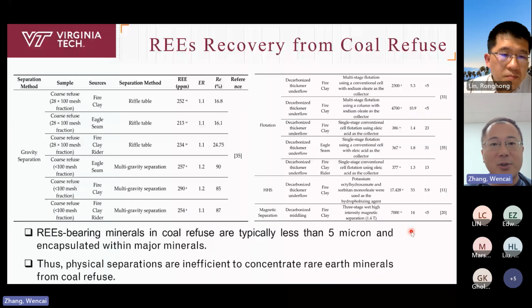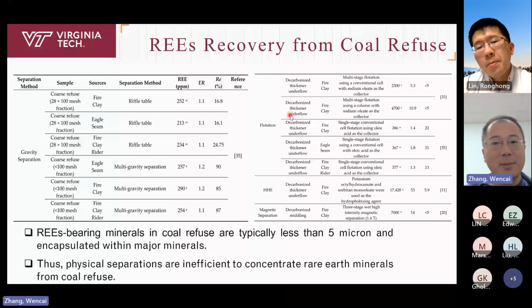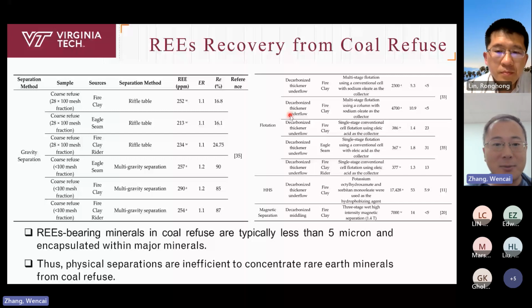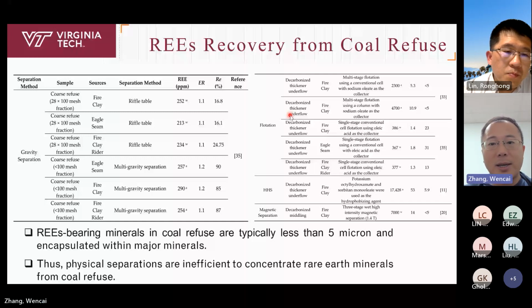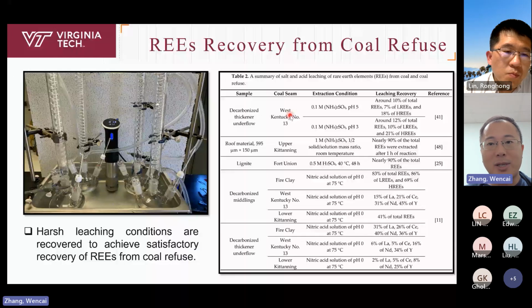So we did a lot of physical separation tests. For example, we wanted to separate the rare earth minerals based on density difference, surface chemistry difference, and magnetic property difference. But we didn't get a lot of success. I think the major reason is that the rare earth mineral particles are so fine in coal refuse, mostly less than 5 microns, and sometimes those particles are encapsulated with major minerals. So in this case, it's very difficult to use physical separations to separate the rare earth mineral particles from the other particles. So lately, we did some chemical recovery work.